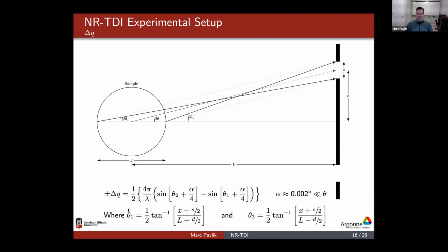So the Q resolution is based on these angles. If this is my sample, this is my slit width, this is the distance or the radius to the center of my slit, and then the distance between the center of the sample to its slit width itself. So L is what we use to determine the momentum transfer, the Q value, and the other values are relatively fixed as we do this. But this is the geometry that determines what the delta Q resolution is.